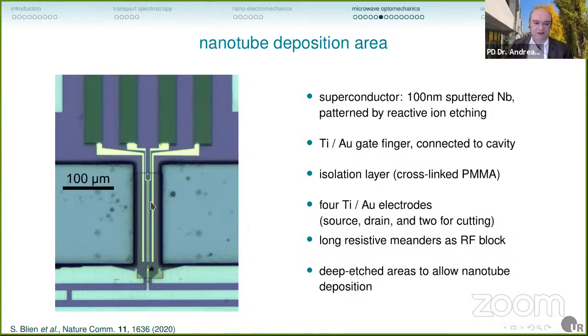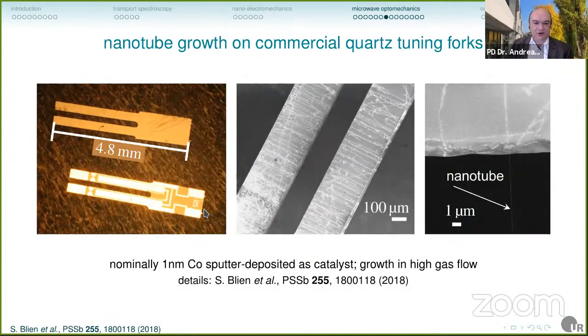On the left side and on the right side, there are two deep-etched areas, two holes, which allow us to deposit the carbon nanotube. How do we do that? Well, we grow our nanotubes on tuning forks. These are exactly the tuning forks that we all know from quartz watches. It's just one piece out of a quartz crystal. We remove the metal, we put catalyst on top, then we grow nanotubes.